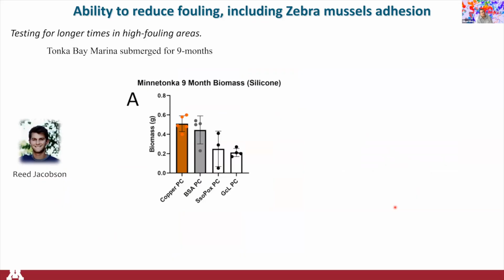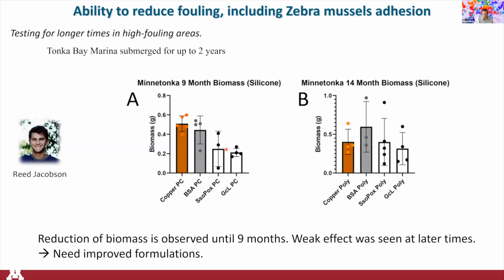Now, we repeated these experiments later with the help of Reed that measured those samples for 9 months, but also up to 24 months. And he could see some reduction of the biomass and zebras for our lactonase after 9 months of submersion. But what he didn't really see is a strong signal for reduction of biomass and zebra mussel attachment after 14 months, and as well as after 2 years of submersion. And so we think that because those were made with some of our first formulations, this might be due to some loss of activity of the enzyme in this coating, and we're excited to be able to test those new improved formulations that we think are a lot more durable in these conditions.